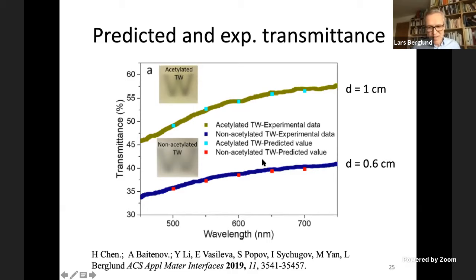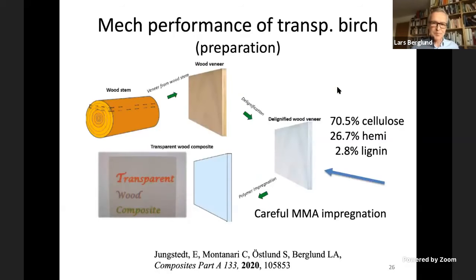And you also notice that if you don't acetylate your wood substrate, you have much lower transmittance. And in this case, the reason is that you have delamination between your polymer and your wood cell wall. If you acetylate, you reduce the amount of moisture in your material. Even if you dry your wood substrate, there is enough moisture there to influence your adhesion between the polymer and the cell wall. So this is why we get better results for acetylated wood.